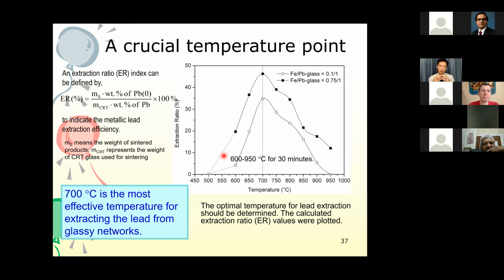This everything is still inside the sample. How much lead right there? You use chemical method, chemical composition, still the same. The lead is still inside there. It doesn't matter whether it's in the metallic lead zero form. It's still the same. So you have no way to use chemical method to do such characterizations. XRD is the way to do it.